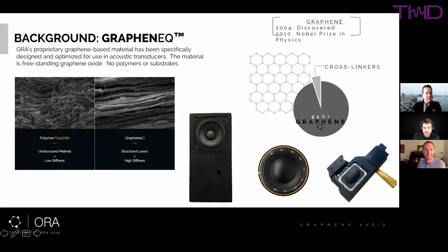As long as I'm on this slide, I also may as well point out that this is an electron microscope image of the edge of the material. So if you look at the edge of the material under electron microscope, you can actually see these layers of graphene that are then held together with our cross-linking agents.